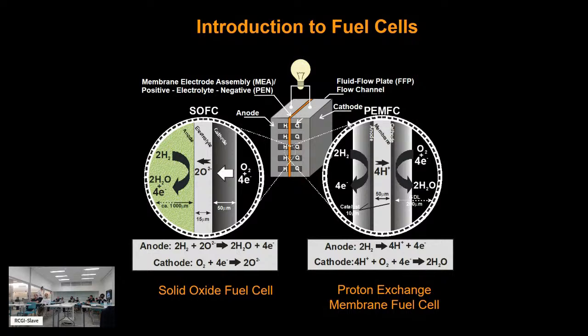We get a voltage generated based on the thermodynamic driving force, the free energy in the reaction, which defines the voltage. The voltage is a thermodynamic property. So voltage defines efficiency, because the free energy defines the maximum efficiency. So voltage equals efficiency: the higher the voltage, the better from an efficiency perspective. And as you get electrons flowing around the circuit, that's current. So current is reaction rate: the higher the current, the higher the reaction rate. One of the joys of any electrochemical system is that you measure the current and you absolutely know the reaction rate, which is much harder to do in a conventional chemical process, but in an electrochemical process becomes very precise.